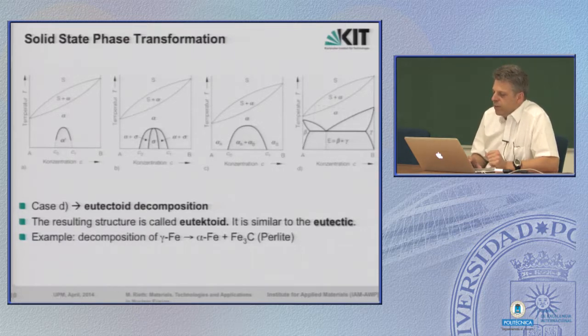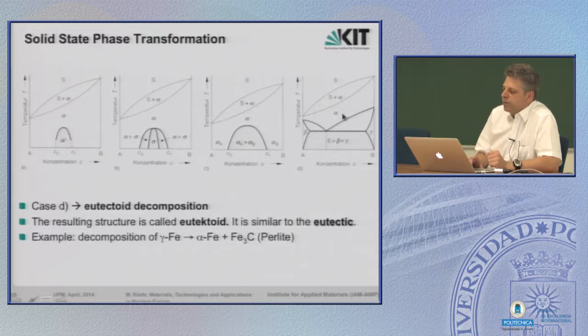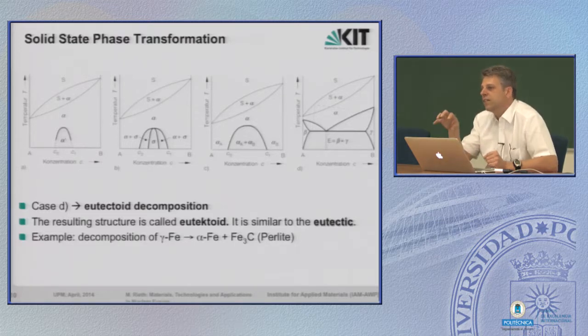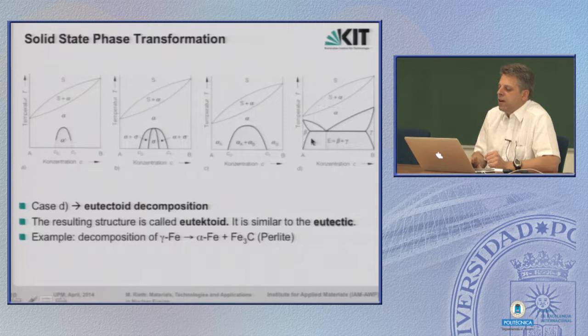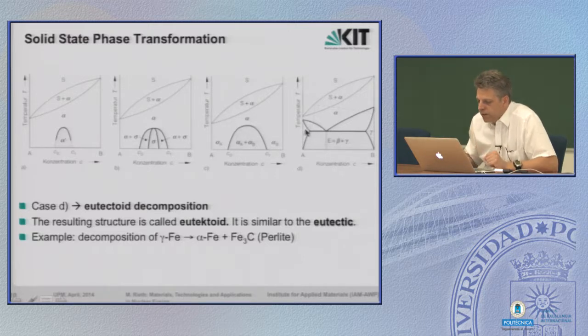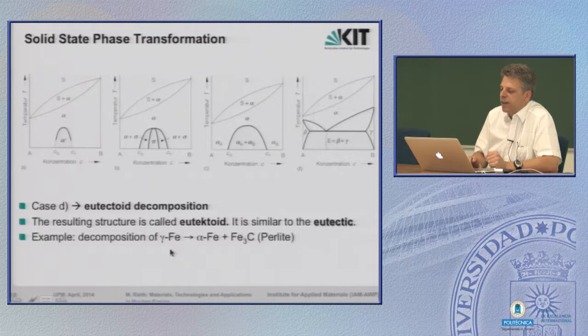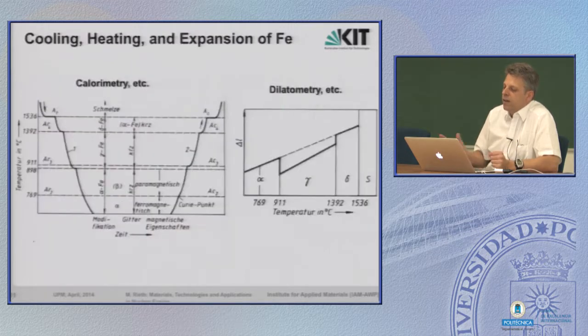This one here is a mix of the two fundamental phase diagrams. First, we have again transformation in the solid solution, and then the solid solution, depending on the concentration, can show further segregation as we had before. But in this case, the decay or decomposition starts in the solid phase, not in the liquid. And here, a very important example for this type of phase diagrams, at least the lower part, is related to steel, to the iron carbon system.